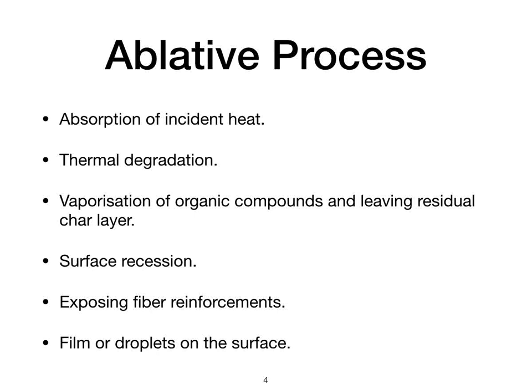Initially, heat incident to the surface is absorbed and then conducted into the material substrate. Heat penetration proceeds at a low rate due to the very low thermal conductivity of the ablator. Surface temperature thus rises rapidly and thermal degradation begins in some form. Organic components of the composite vaporize into numerous gaseous products of varying molecular weights, often leaving behind a residual char layer.